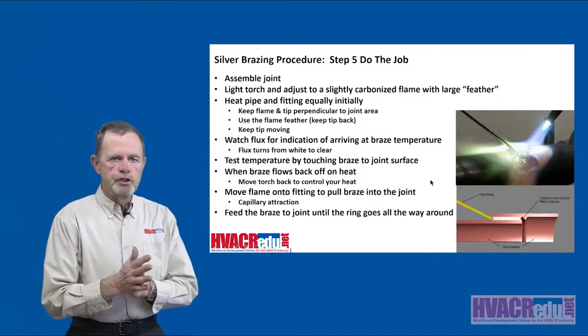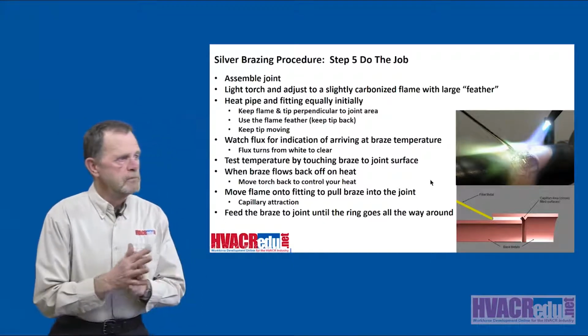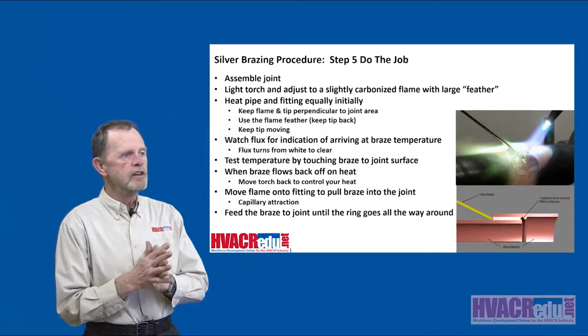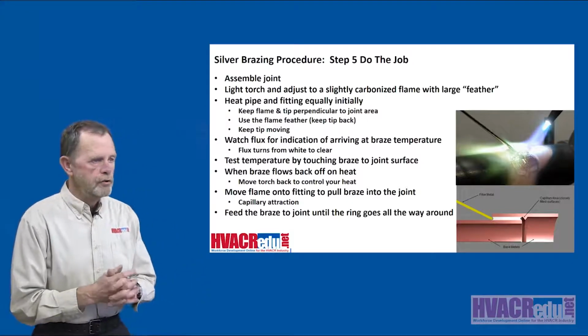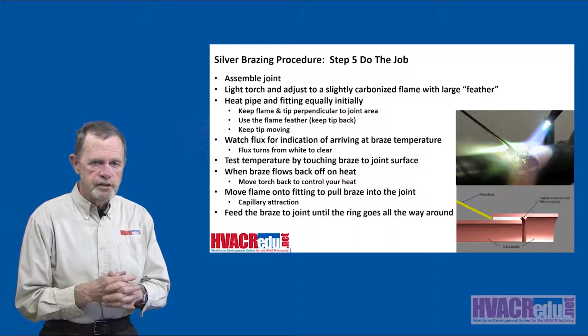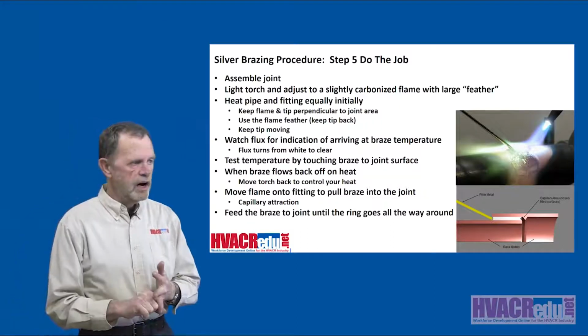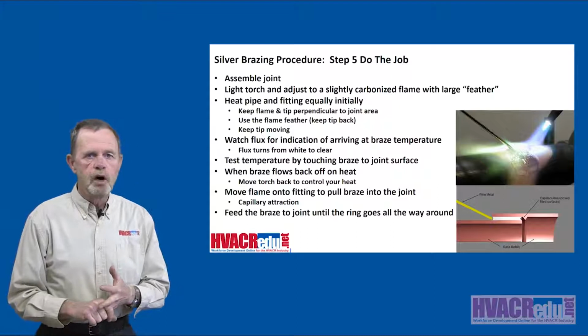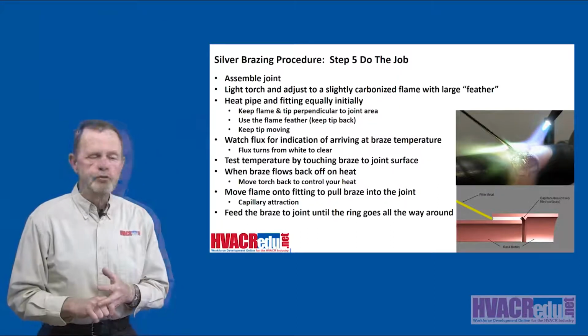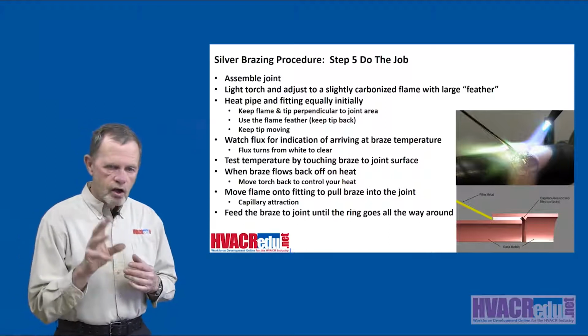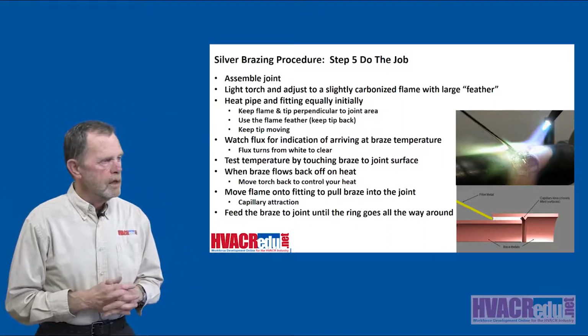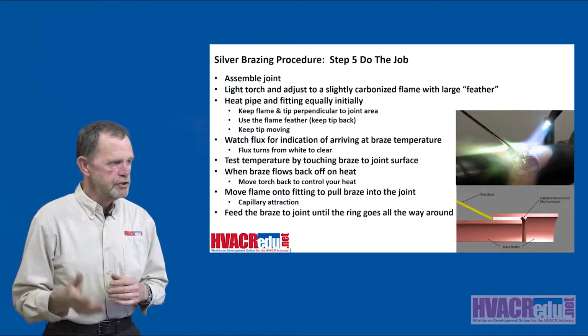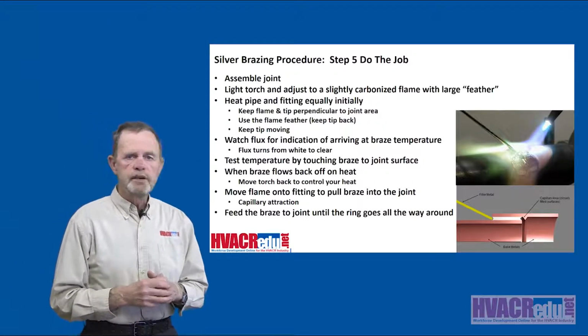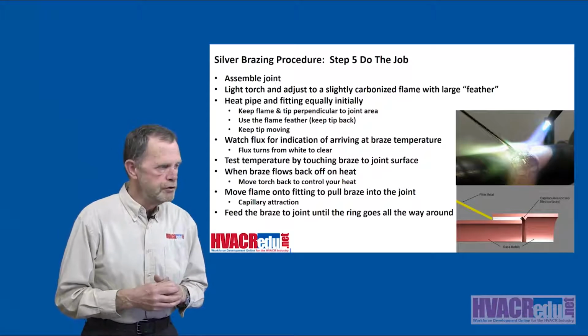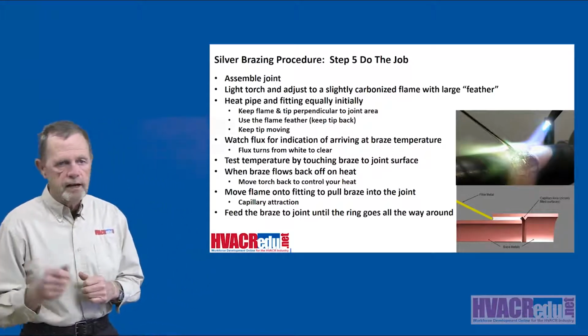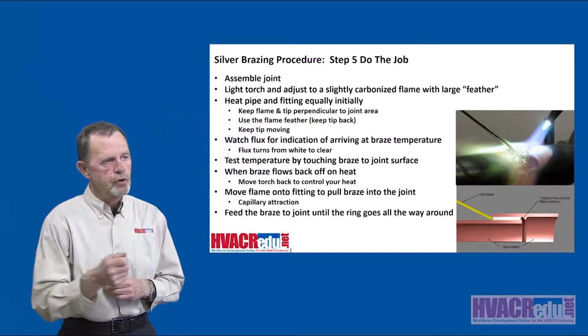Step number 5, do the job. Assemble the joint, light the torch, adjust to a slightly carbonized flame with a large feather. And you saw that in previous sessions when I talked about soft solder or Silphos. That feather is what you want. You don't want a hard, neutral flame even. You want a soft, slightly carbonized flame. Heat the pipe and fitting equally on the initial setup. Keep the flame tip perpendicular to the joint that you're doing. Use the flame feather, keep the tip back. Once again, that's all about controlling heat.